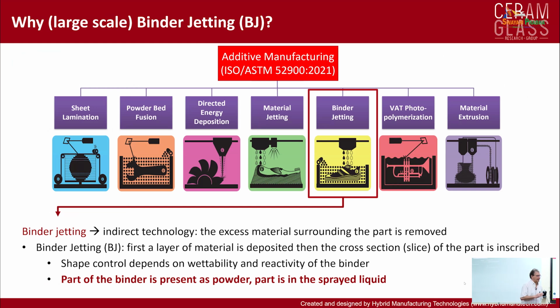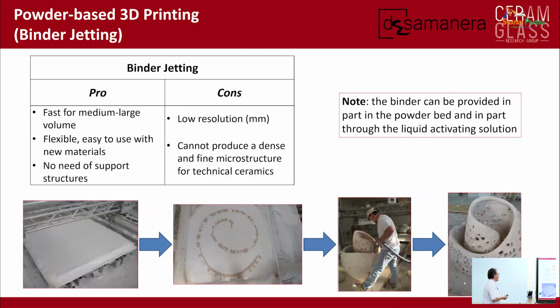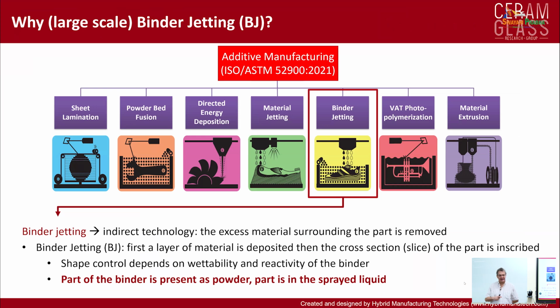Another additive manufacturing approach that we use for printing components using geopolymers is binder jetting. In our case, part of the binder is present in the powder bed, and we spray a reactive liquid. Because of the reaction between the binder in the powder bed and the reactive liquid, we form a bond in the powder bed, and the particles get bonded. Specifically, we are using metakaolin in the powder bed, and we are using an alkaline solution as the reactive liquid.